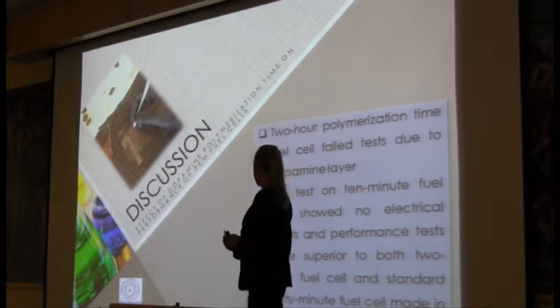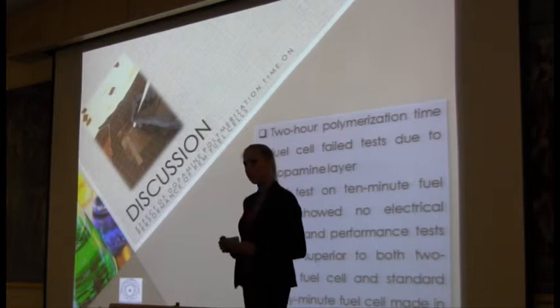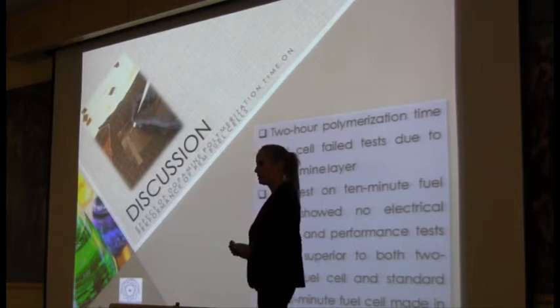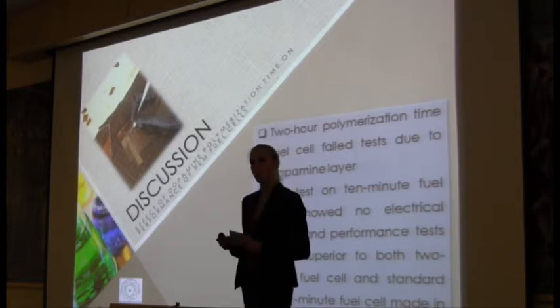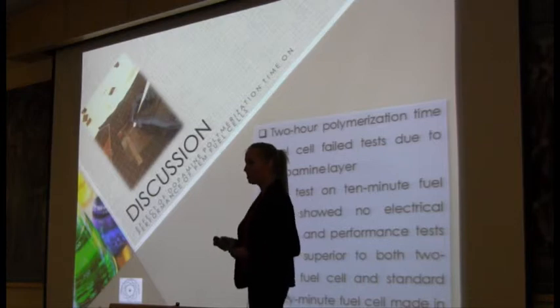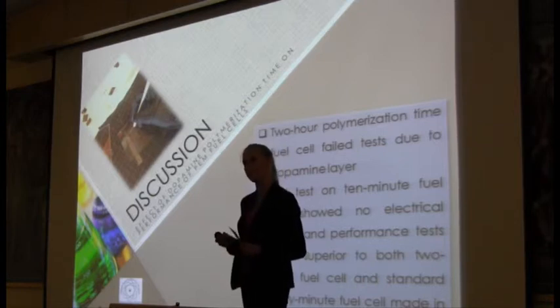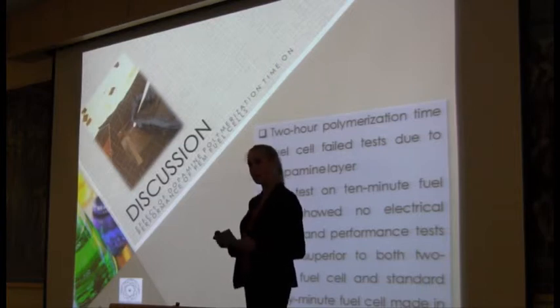The reasoning behind the 2-hour polymerization time fuel cell failing is because, as I mentioned earlier, dopamine self-polymerizes in the presence of oxygen. So when the membrane is immersed in an aqueous dopamine solution for a longer period of time, it allows the dopamine to self-polymerize for a longer period of time, and that makes a thicker layer of dopamine on the membrane. This thicker layer of dopamine blocks protons from flowing through the membrane, which resulted in the malfunction of the fuel cell.